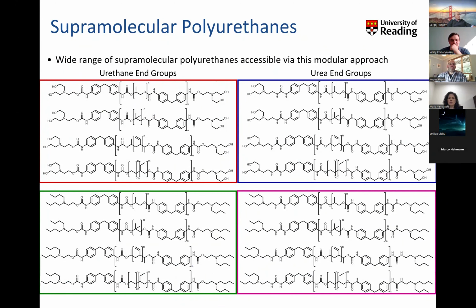But if we alter the nucleophile in the last stage of the reaction sequence that I showed you to an amine, we can make the urea derivatives. So we have comparable materials in terms of molecular weight and molecular composition, all bar the change of a urethane end group to a urea end group. So we're literally changing an oxygen for an NH in the corresponding ureas. And that enables us to do a lot of molecular engineering and dive deeper into structure property relationships.